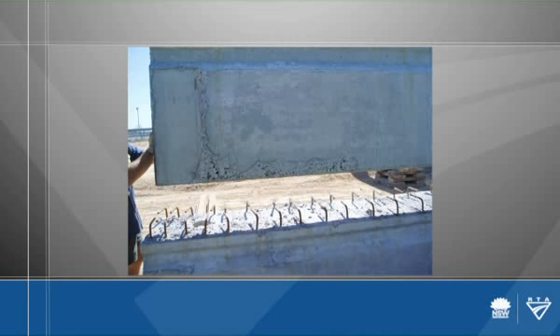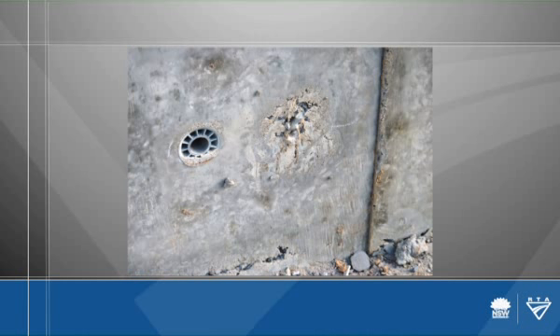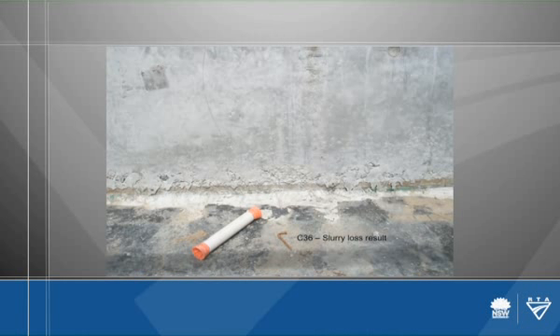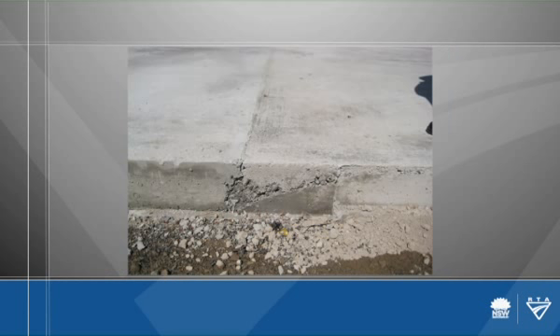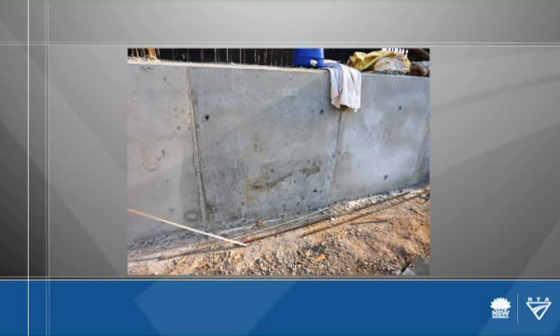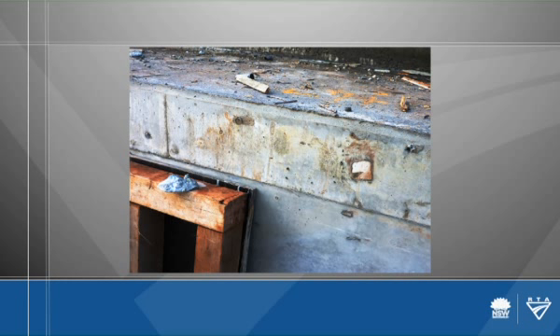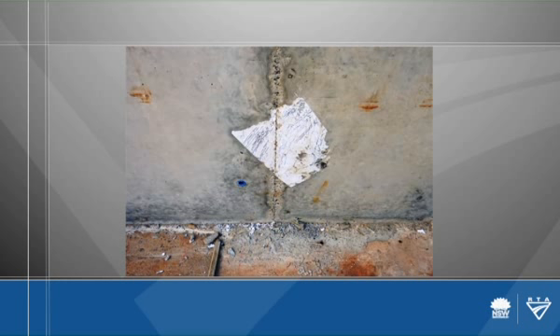So Don, are there any other avoidable defects we need to be aware of? Well, other avoidable defects include honeycomb, which may be caused by lack of compaction, but it also may be caused by slurry loss from the formwork. So in other words, the formwork hasn't been sealed properly. You may have cold joints in the concrete where there's been a delay and the 2 layers have not been integrated, so we end up with a line in the concrete surface. You may have burn marks on the formwork as a result of someone touching the form with a vibrator. And you may have foreign materials that have got into the formwork that haven't been cleaned properly when they should have been before the pour.